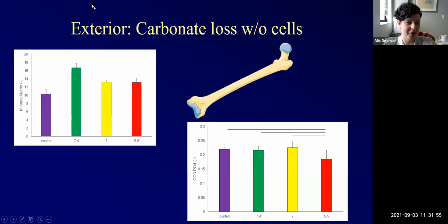Here's my exterior Raman. As you can see, my mineral to matrix ratio doesn't change, just like what I saw in my in vivo system. Taking a bone, putting in an acid, even at 5.5, I do not see a change in mineral to matrix ratio on the bone surface. I do, however, see a decrease in carbonate. This is behaving exactly like my in vivo system. Decreased carbonate, no change in mineral to matrix.